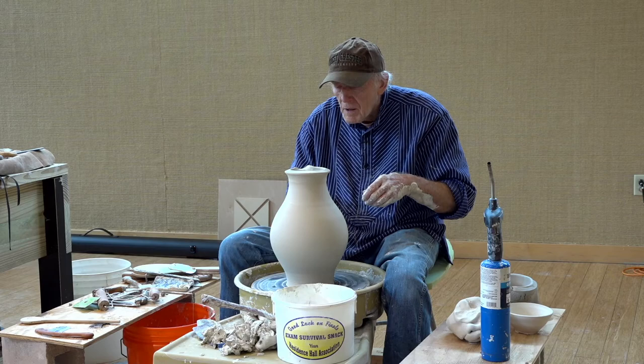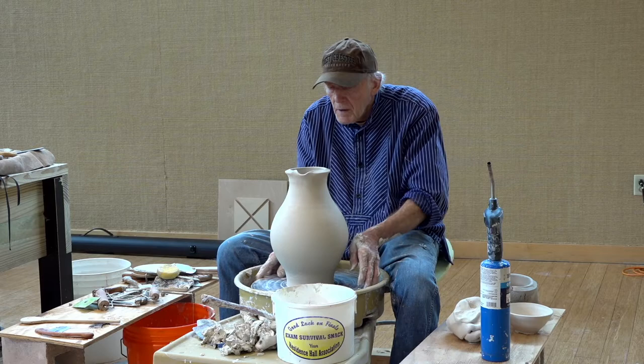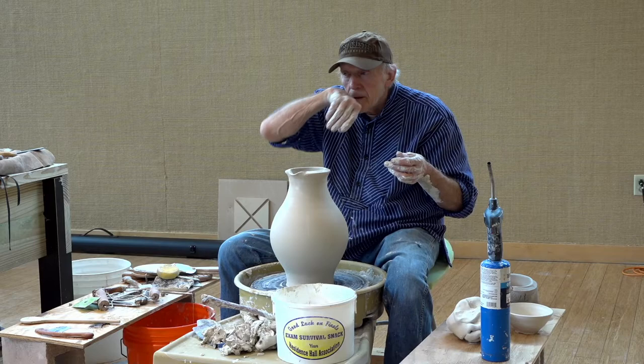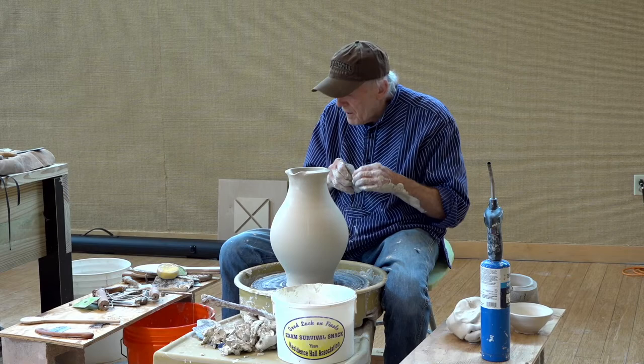And I'm very careful. I have a big slab of stone on the wood stove, and I put them on there and make sure they're extremely dry. As a matter of fact, I hang a 100-watt light bulb down inside overnight, right where the handle's attached, because this is very fine clay. It's almost like porcelain. It has no texture, no grog. I want to make sure those handles stay on. And I haven't lost any since then. I was just sloppy, I guess.